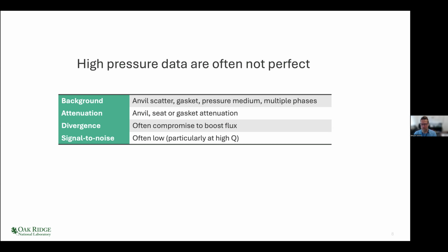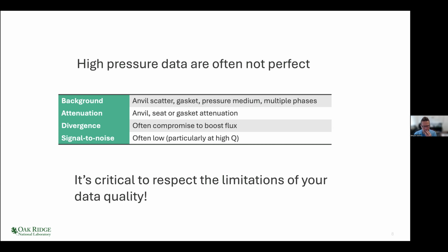Traditionally, signal to noise is bad for neutrons, but if you look at X-ray data from light materials, there's normally a very high Compton background, which is higher at high Q, which is high angle. And so signal to background can also be a challenge for X-rays. And it can't really be overstated, but it's critical to respect the limitations of your data quality and just not overinterpret where the information is not present.